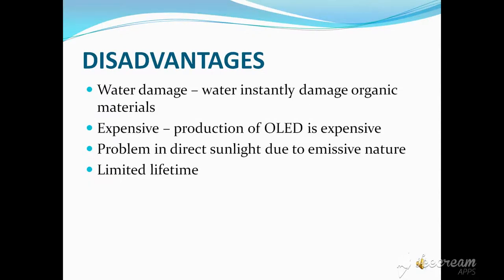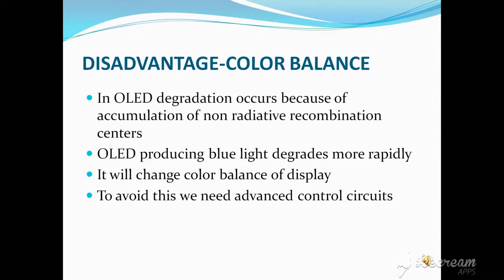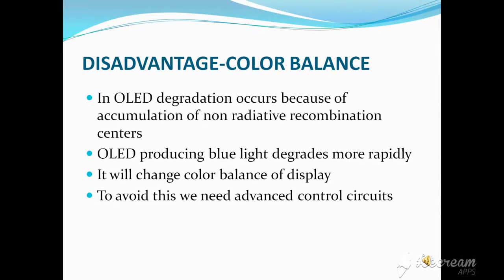Disadvantages of OLED: water can instantly damage organic materials used in OLED. It is expensive to produce, though in future it may be of lower cost. There is a problem in direct sunlight due to its emissive nature. OLED also has a limited lifetime. Another disadvantage is color balance — degradation occurs because of accumulation of non-radiative recombination centers. OLED producing blue light degrades more rapidly, which changes the color balance of the display. To avoid this, advanced control circuits are needed.